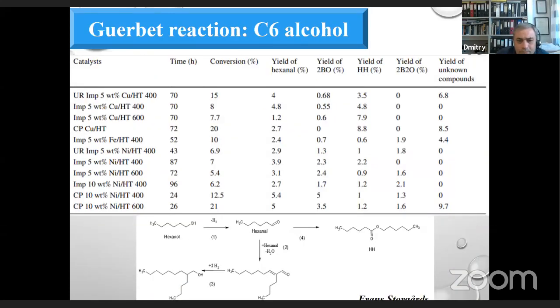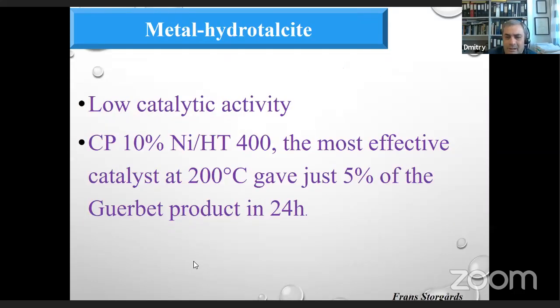Let's look at the results. Different catalysts were made here. You see the reaction time was pretty long, and here we see levels of conversion that are not very high, and once again our desired product is something like that. So the yields are pretty low, whatever we tried. Once again, we need to have a dehydrogenation reaction requiring a high temperature, and then we need to have a hydrogenation reaction, which would probably run more efficiently at lower temperatures. So low catalytic activity altogether, and the best catalyst, the most effective one, gave just 5% of the desired Guerbet